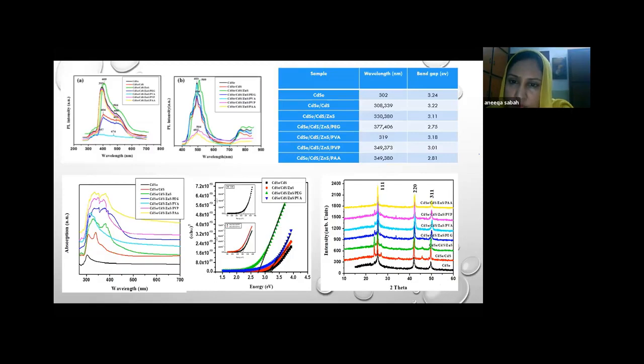The band gap showed a decreasing trend as you go to the quantum dots and PEG. But when you add organic and inorganic ligands, there is a little increase, but this increase is basically because we are coating the material, so the band gap size increases, but they are still in the quantum regime for the one-dimensional materials - their diameter will be in the quantum regime.